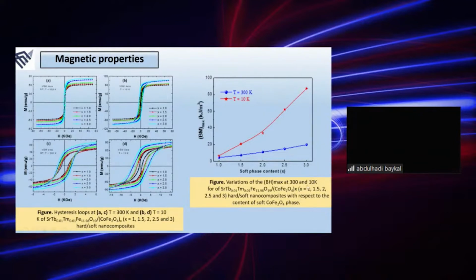So this is the (BH)max variation of our samples with the soft content. You see that at different temperatures, at 10 Kelvin and 300 Kelvin, or room temperature, this shows the variation of the hard and soft. And the graph on the right side shows that at low temperature, (BH)max is increasing gradually with the soft content, I mean the x values. Now let's have a look at this.